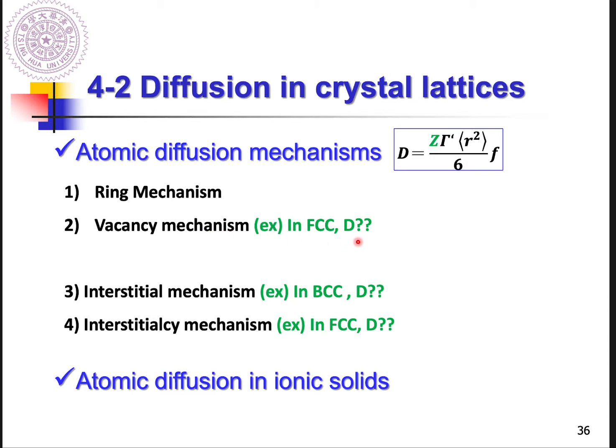In this kind of case, the self-diffusivity of the host diffusing atom is proportional to the atomic vacancy fraction, the diffusivity for vacancy, and the correlation factor. And it is also proportional to the exponential of the vacancy formation energy plus the vacancy migration energy.